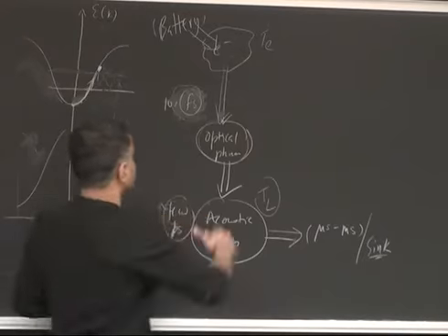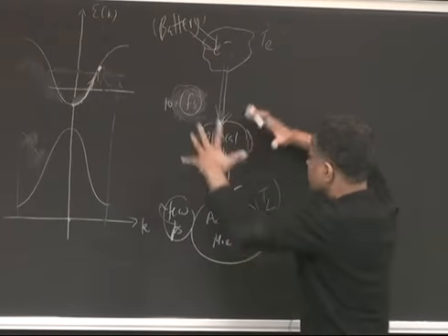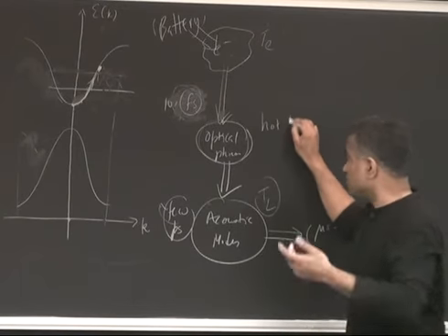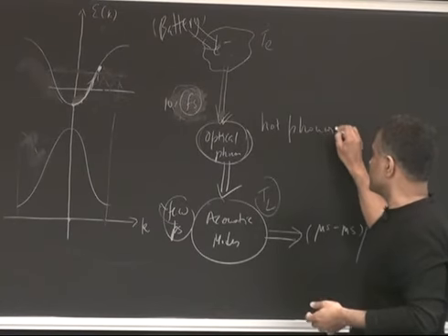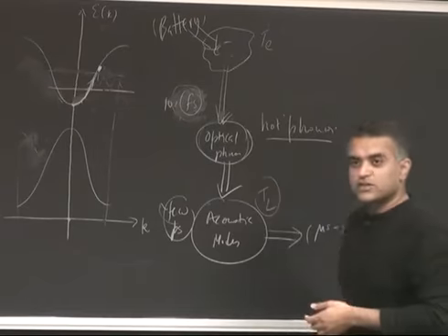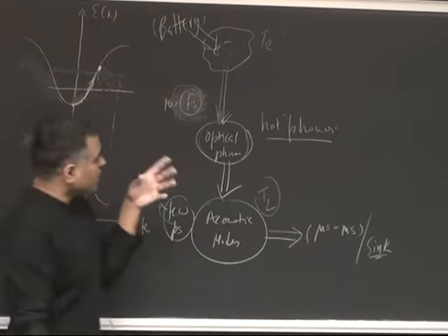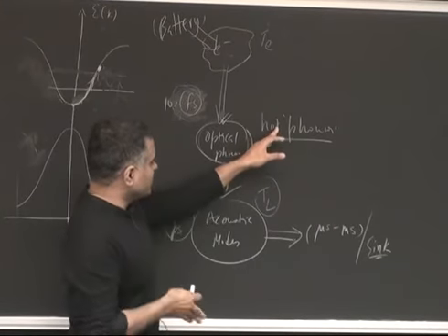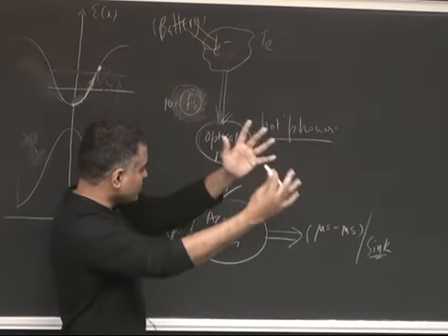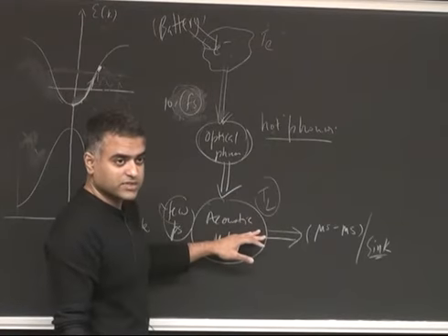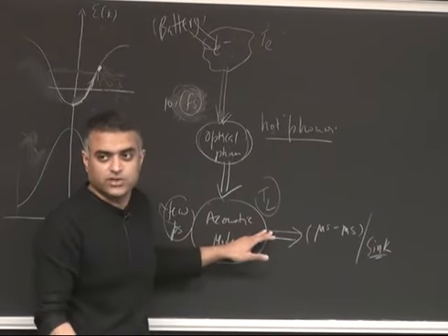So what happens is a lot of energy is also stored in the optical modes. That's sometimes called a hot phonon, which is an interesting name because phonon is heat itself, but it's a non-equilibrium phonon, way out of equilibrium. If you measure the optical phonon distribution, its effective temperature that fits the Bose-Einstein distribution, for example, is way higher than the physical lattice temperature. The lattice temperature is related to acoustic phonons and the vibration.